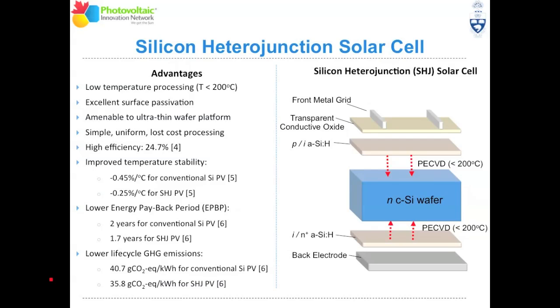So the hydrogenated amorphous silicon, in addition to providing the rectifying and back surface field junctions, also passivates the crystalline silicon surface. And in crystalline silicon, most of the defects lie on the surface. And so if you're able to passivate that surface, you can get really high efficiency solar cells. And this has been demonstrated recently.